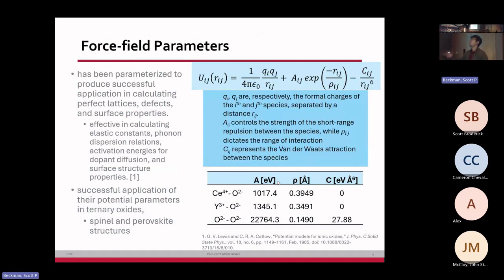This interatomic potential basically has a part that accommodates the electrostatics, the van der Waals attraction at the long range, and also the repulsive force in short range. This particular potential has been used to produce lattice parameters and defects, also has been successfully employed in elastic constants of the solids, and also the phononic dispersion properties.